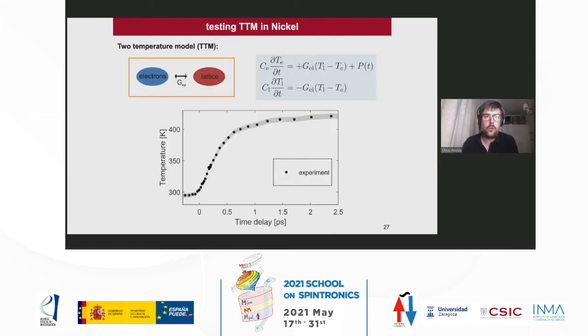So we wanted to use just the most basic two-temperature model to check the parameters and the ultrafast dynamics of the lattice, to make it simple. We have the heat capacities from the electrons and lattice, their temperature dependence, electron-phonon coupling, and these are the experiments. So what we did is plug in all these parameters and calculate the dynamics of the lattice, and this is what we got.